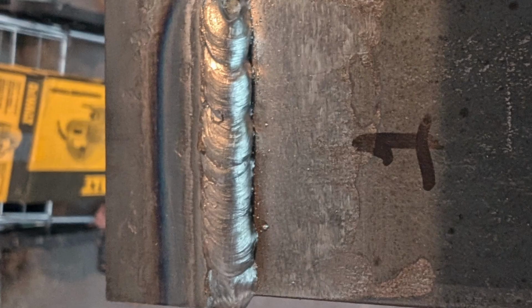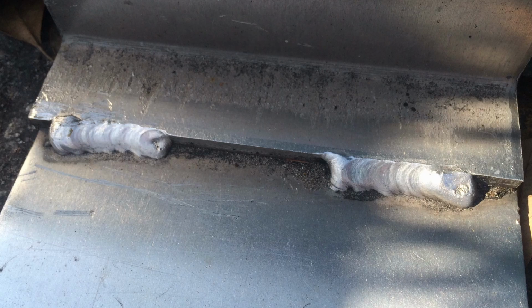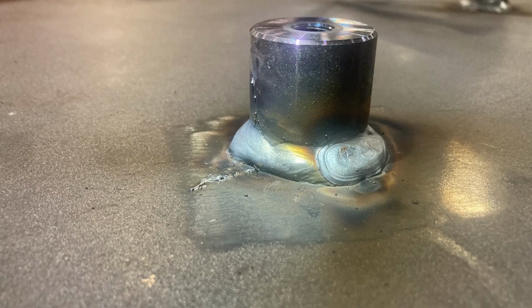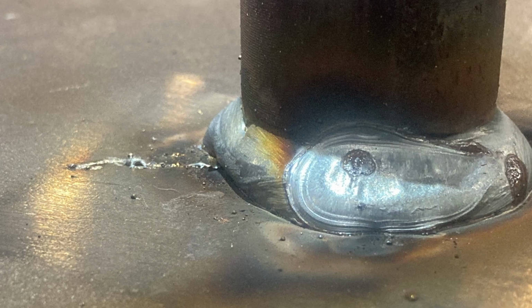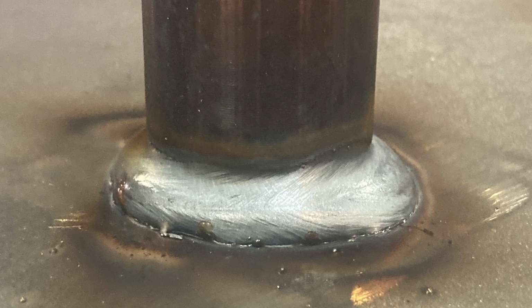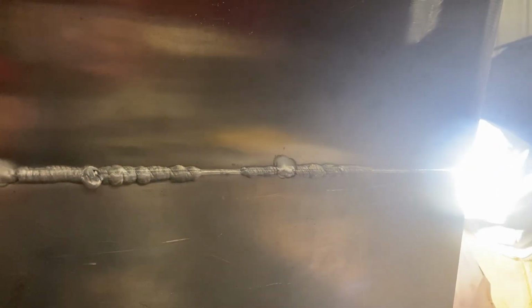Incomplete fusion is another weld discontinuity that may result in a poor weld appearance and what they call overlap, where the top of the weld reinforcement sags over the reentrant line where the weld metal joins back into the base metal. Arc strikes outside the weld zone are another discontinuity. Some welds may have more than one discontinuity. For example, a poor profile with overlap is often indicative of undercut on the top side of the weld toe. Incomplete penetration could be another weld discontinuity.